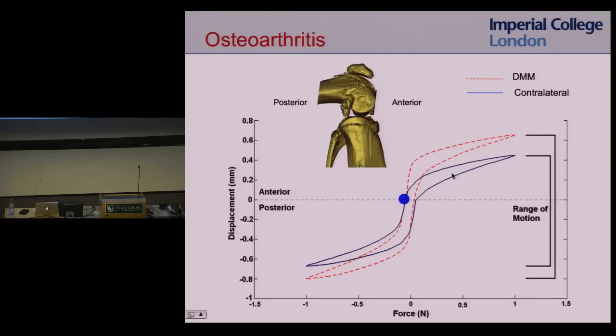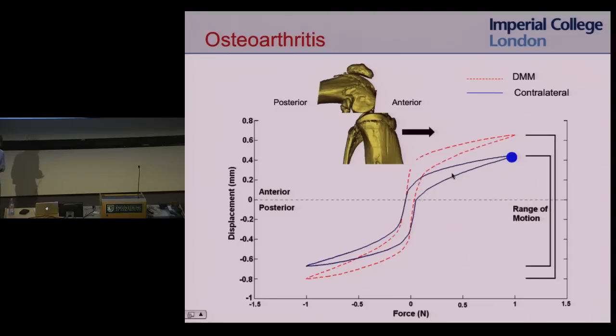We start at zero force. We then pull the tibia posterior or backwards until negative one newton force. We then put it back and push it forwards to positive one newton force. So it's force controlled, and we're measuring the amount of displacement as we move it back and forth. So you can see this is the control leg. So this is the non-arthritic leg. In the side that has the injury, where we've cut the meniscus, we see a much higher range of motion. So it can move much further forward, so particularly in the anterior direction.